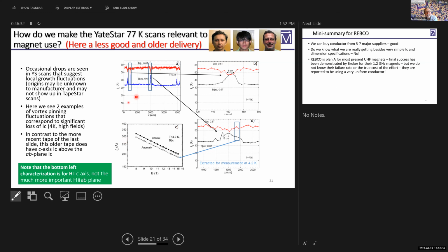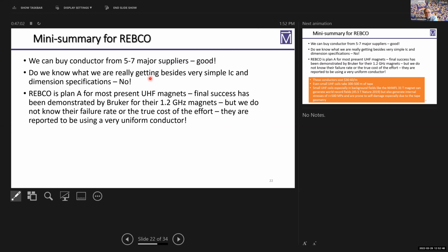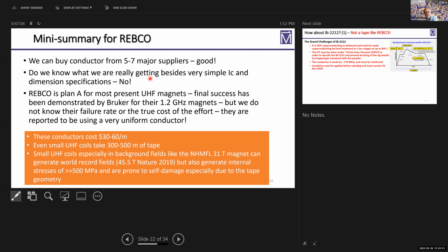And sometimes, in fact, you see as they lose control, maybe in this case it's a conductor made by MOCVD, there's an MOCVD burp in the shower head, and that burp actually locally inverts the critical current density, due to the fact that here we lost those C-axis nanorods, and we got some jumbled array of mass. So the mini summary is we can buy conductors from 5 to 7 major suppliers, which is good, but do we really know what we're getting?